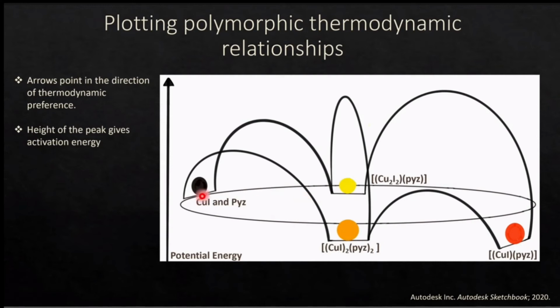So the depth below that circle shows us the difference in potential energy between the reactants and the product. And so we can see that you can go either to orange or you can go to yellow, and that the orange and yellow can interconvert, but the activation energy is quite high, so it doesn't seem to happen very often. And between yellow and red, we know that this took over a month to happen in the previous experiment, so we can see also that that is a very slow, very energy intensive reaction.